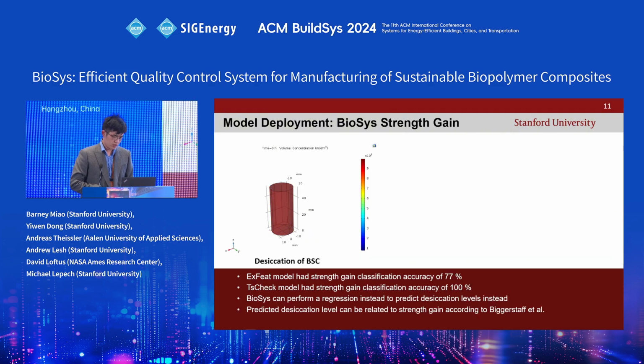Another thing I want to show you, I didn't show the compaction for time considerations, but in this case for the strength gain, another benefit is that this material, unlike concrete, which undergoes hydration chemical reactions, hardens through an evaporation process called desiccation when the solvent leaves the wet mix. Typically in the field, you would measure this on a mass loss basis, so you weigh your samples,